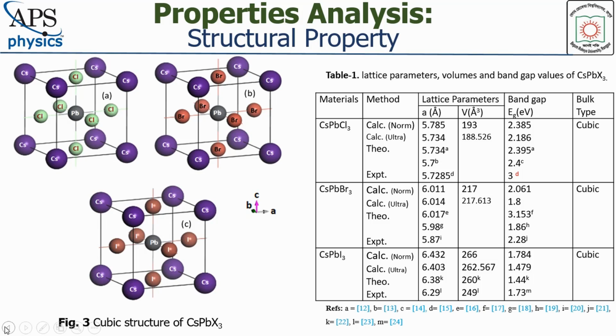The table shows the theoretical results have a good agreement with experimental ones for ultra-soft pseudopotential only for lattice parameters and mechanical properties. Optical properties are closer to experimental values for norm conserving pseudopotentials. With the insertion of bromide and iodide in place of chloride atoms, the lattice parameters increase due to the comparatively larger ionic radii of bromide and iodide atoms. But the opposite trend is observed for the band gap values.